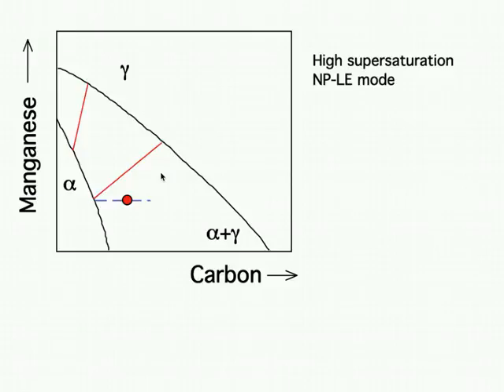If I draw a horizontal construction line through our alloy where it touches the ferrite phase boundary, that defines the tie line governing interface compositions, and you can see that there's very little partitioning of manganese. In other words, we have a steep gradient of manganese to compensate for its low diffusion coefficient, whereas the carbon is now diffusing in the long range. So this kind of transformation would happen at high supersaturations.